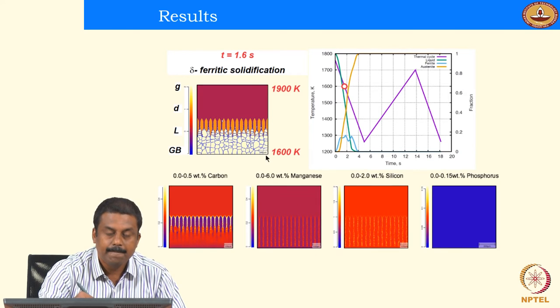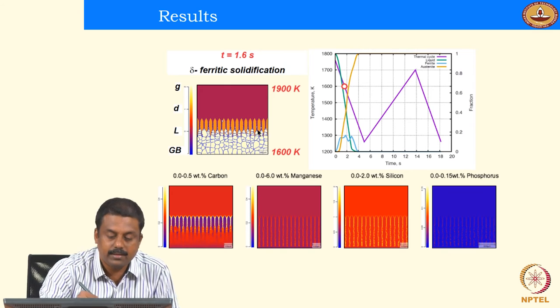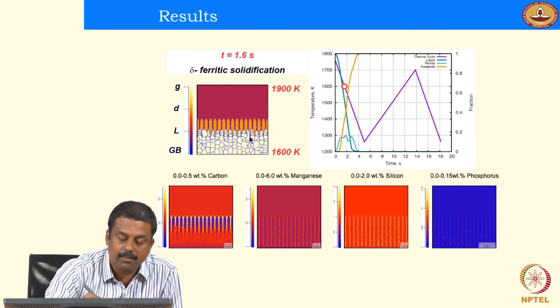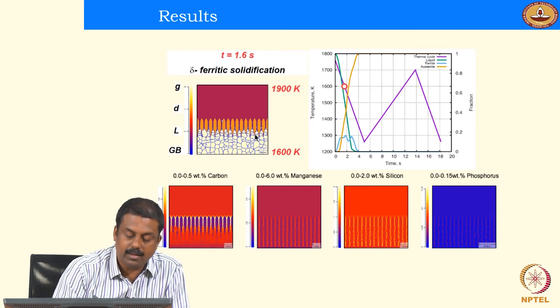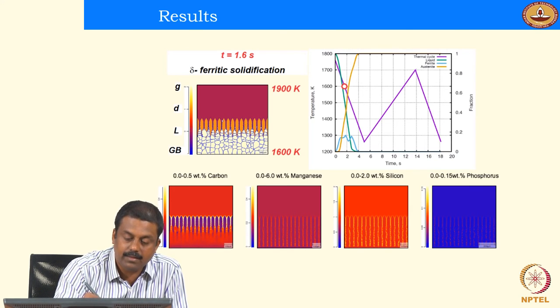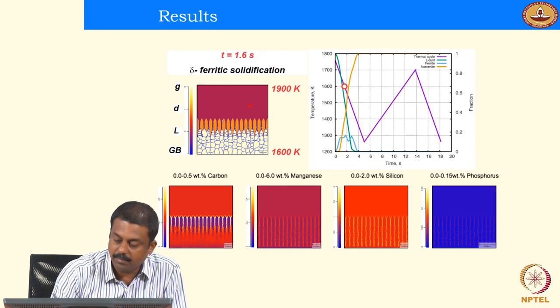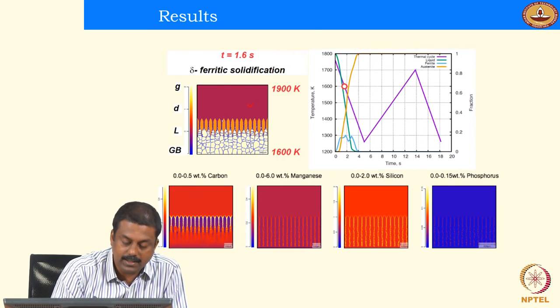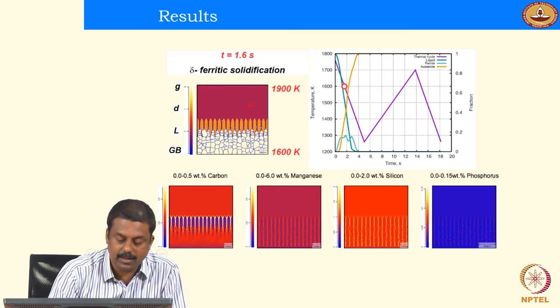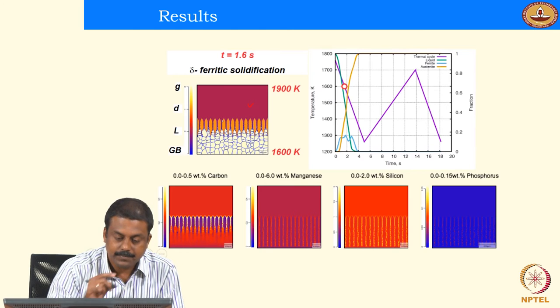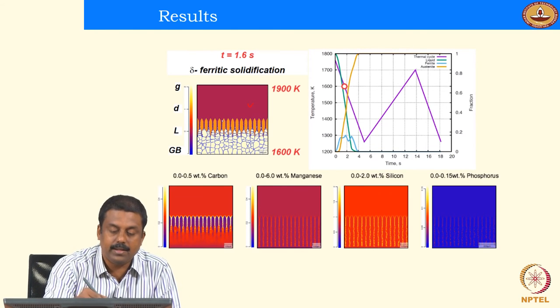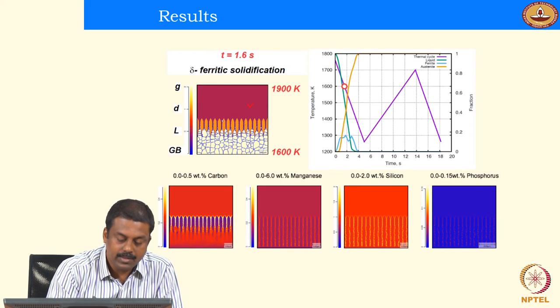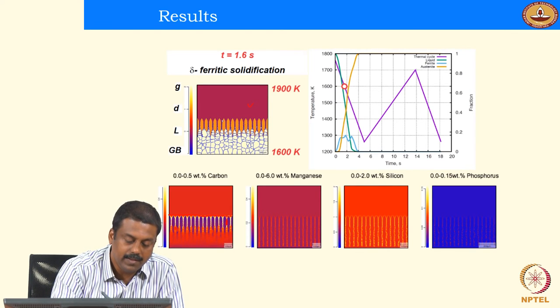you have a partial solidification of the delta ferrite, for example. In this case we have delta ferrite as well as the austenite forming. Okay, and during this process, because of the solubility difference between delta ferrite, austenite and the liquid, you will have a segregation of carbon, phosphorus, manganese, silicon at the interdendritic boundaries as well as at the liquid front. Okay, so you will have a segregation based on the solubility of the elements in delta ferrite, austenite and liquid, and you will have a segregation at the interdendritic boundaries as well as at the solidification front, because that is the region where the carbon atoms are migrating from the delta ferrite to the liquid.